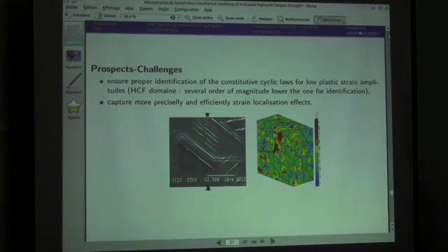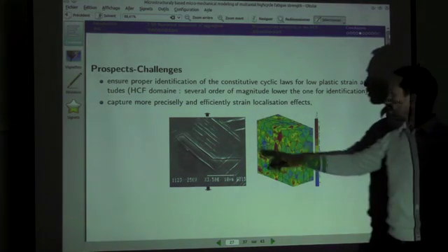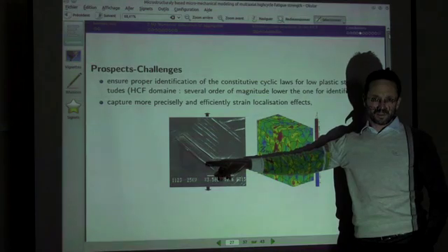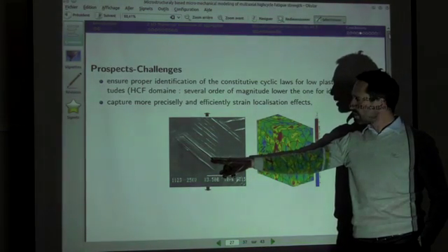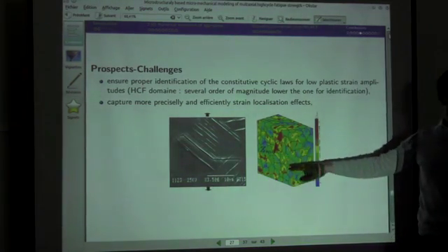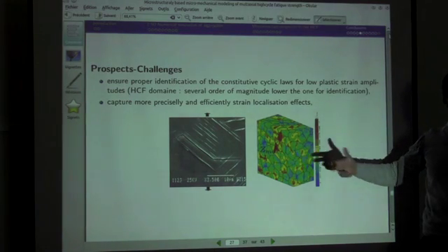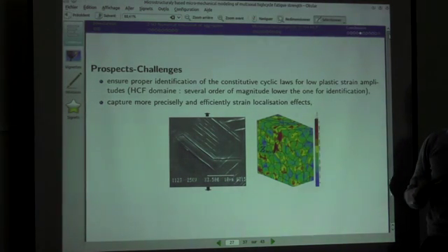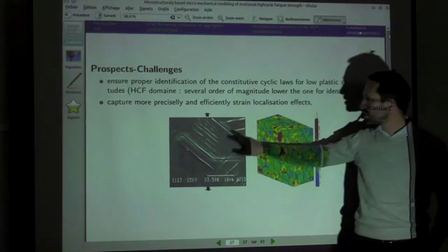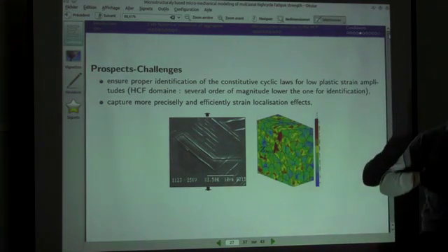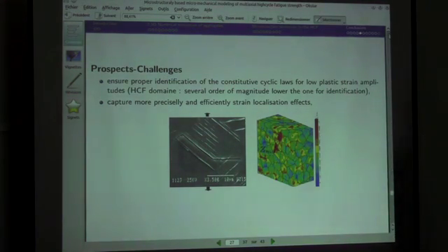The second problem we have is that what we try to do is to measure crack initiation. So you have localization of strain, localization to crack transition, and what we are analyzing is this type of picture. You can see that the localization is not very well captured. At least we don't have this type of patterns occurring.